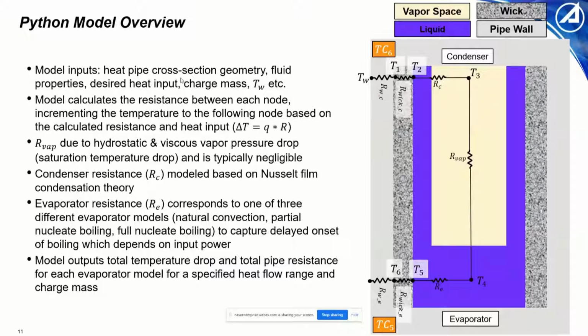The primary model inputs are the heat pipe cross-sectional geometry, the working fluid properties as a function of temperature, the desired heat input value, the charge mass, and the outer wall temperature. For primarily your 2-phase resistances, these values are temperature dependent, so in order to calculate a resistance, you need knowledge of the absolute temperature at that node as well.